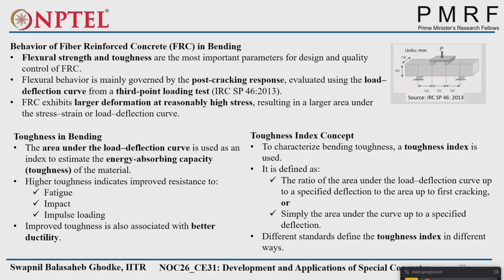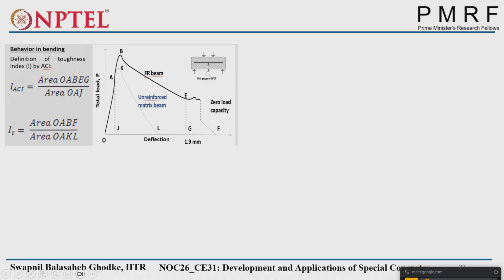So how do we calculate the toughness index? Different codes give different approaches to calculating it. To characterize the toughness index in bending, it is the ratio of the area under the load deflection curve up to a specified deflection to the area up to first cracking, or simply the area under the curve up to a specified deflection. This is the graph we have, total load versus deflection for the fiber reinforced beam, and this is the unreinforced matrix beam, JKL. The definition of a toughness index is the area OABEG, up to a specified deflection, up to 1.9 mm deformation, divided by the area under OAJ. That is called the toughness index according to the ACI.